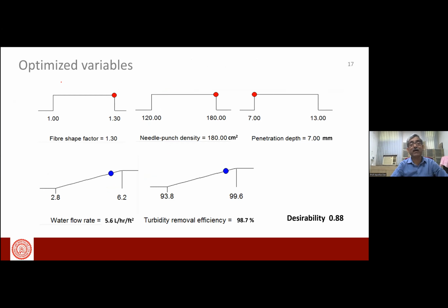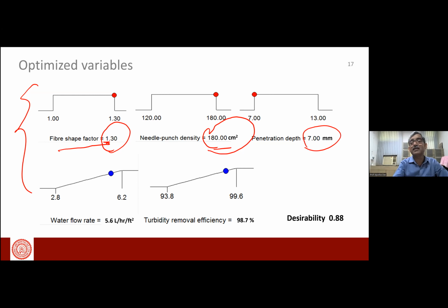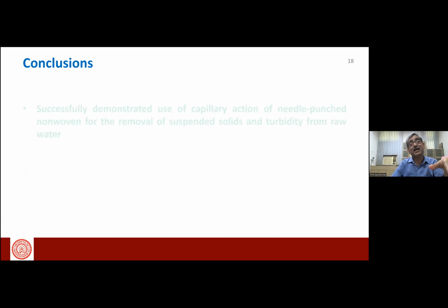So these are the different studies, and finally we could optimize the values. What we have optimized using the fiber shape factor 1.3, needle-punch density is 180, and depth of penetration. This is the first stage filtration, and these parameters we have used in further study.